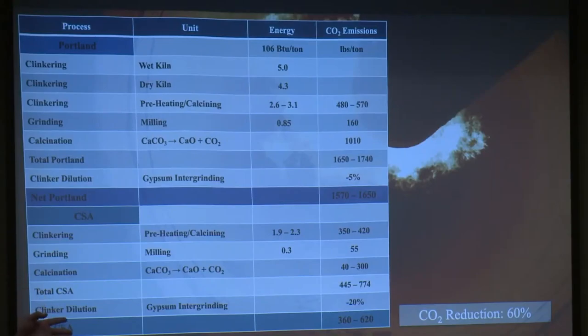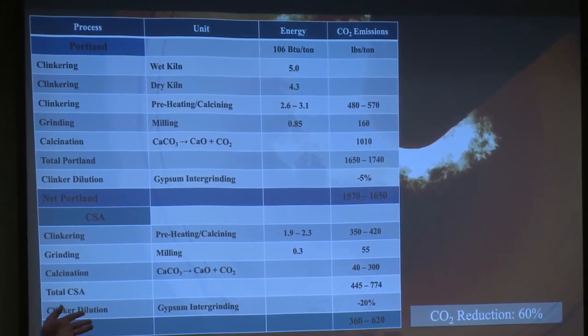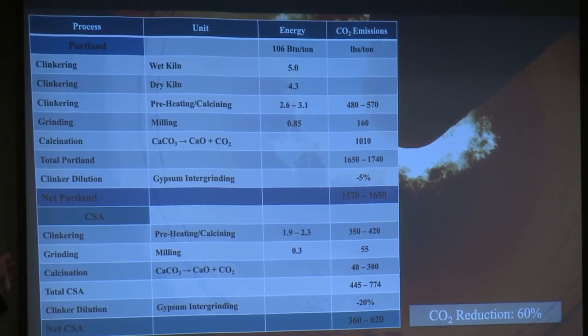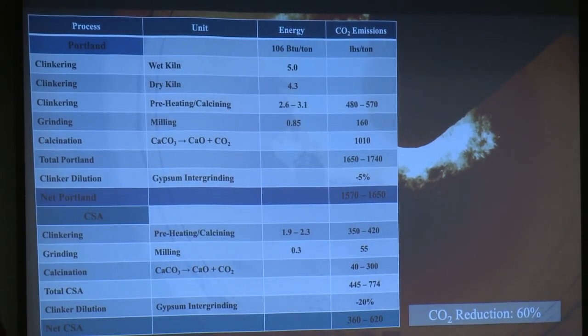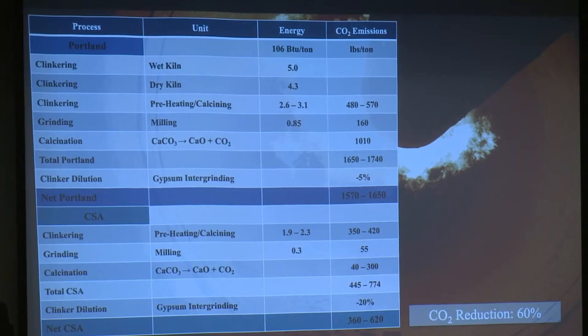And here are some numbers for you to consider. This is from the International Energy Agency, DOE, and some verbal communication with cement plants. We're looking at the various contributions of the processes for developing the cement. The total for Portland was around 1650 to 1740 pounds of CO2 per ton. There's a slight dilution factor when gypsum is blended into the final cement to prevent flash set, so you're looking at around 1570 to 1650 for Portland. CSA is a sulfated cement, so you're able to add around 20% gypsum, which brings you down to around 360 to 620 pounds of CO2. So just by shifting to a different cement type, there's a great influence on the amount of CO2 produced.